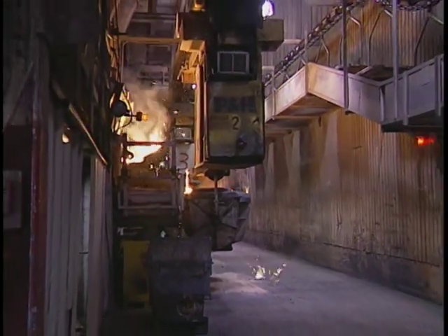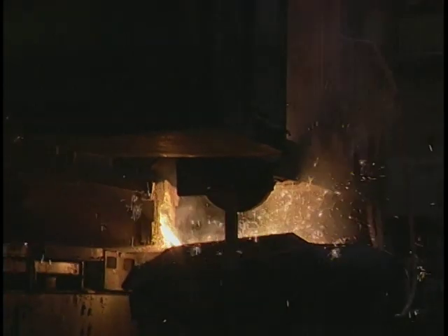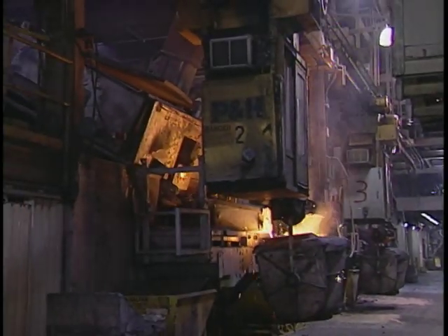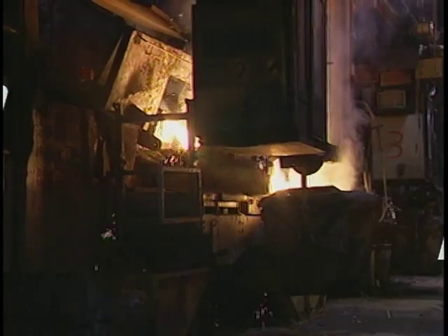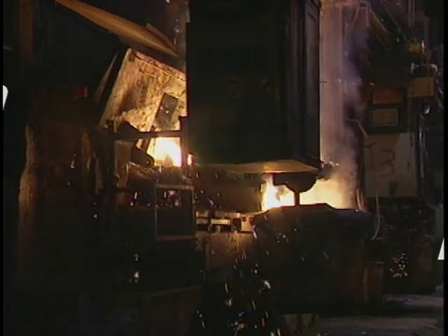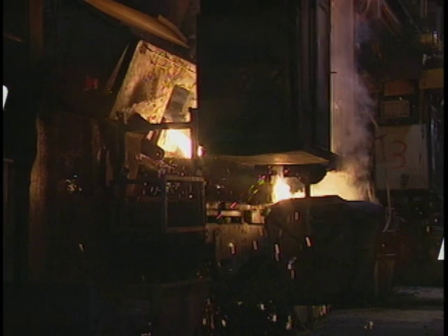When the scrap is melted and poured, it emits fumes which, if inhaled, may be hazardous to a worker's health. This risk is especially great if the original scrap material contains unknown contaminants or toxic components such as lead, nickel, and chromium. As the molten metal leaves the furnace, it vaporizes and condenses in the cool air into extremely fine particles called fumes.